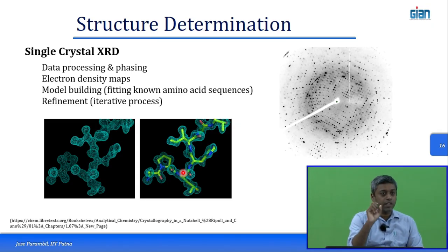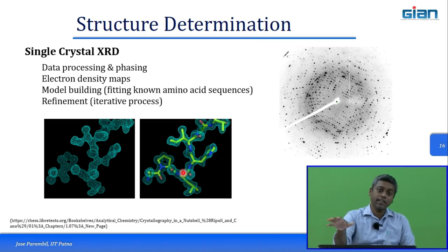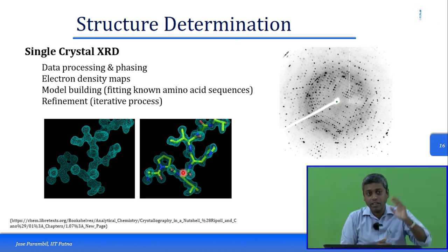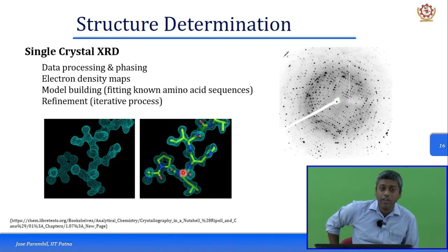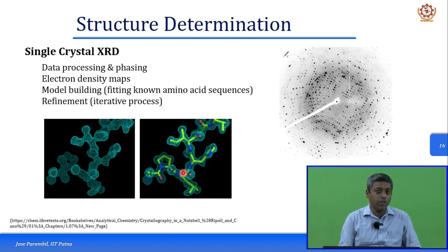Of course, the resolution and other details matter depending on how well you are doing, how good the machine is, what temperature you are working at, and so on. Sometimes, to get very thorough knowledge, you need to cool to cryogenic temperatures to make sure all the molecules are arrested in their positions, and then do multiple XRD measurements to overcome the noise. Even then, in most cases, you do not get much information regarding, for example, hydrogen. Most often, you do not see hydrogen in the simplest XRDs.